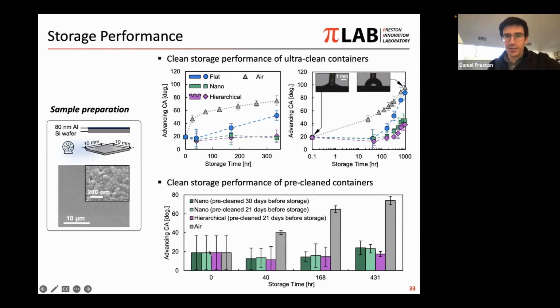And in all of those cases, both the nano and hierarchical textured container walls far outperformed, first of all, the air at 0 time, and second of all, outperformed what your expectation might have been for having let them sit with nothing in them. So this is sort of showing that you can just fabricate this container, let it sit for a month, then put your sample, and then it still keeps the sample clean for hundreds of hours.